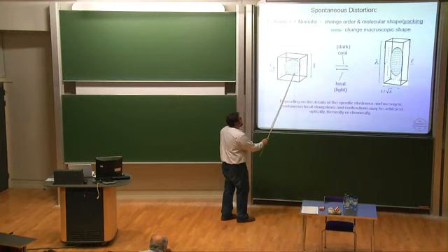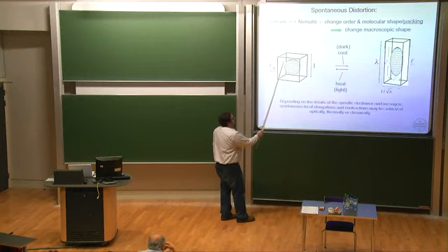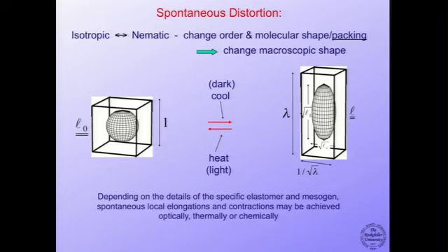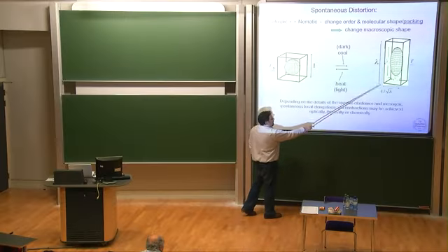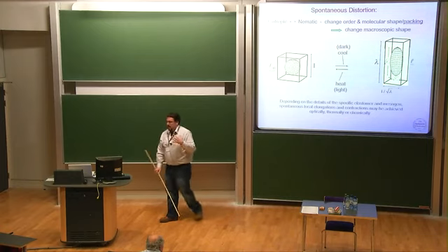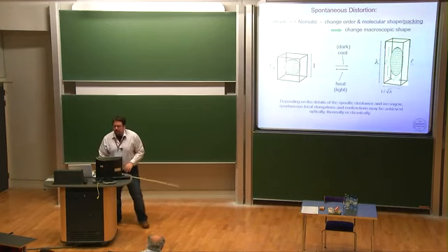If you imagine starting in an isotropic state and cooling down and increasing the order parameter, you'll get longer length scales along the direction of the director field, and you'll get some Poisson shrinking in the directions normal to the director field. These microscopic local deformations are at the heart of all the deformational things you can think about doing in these systems.